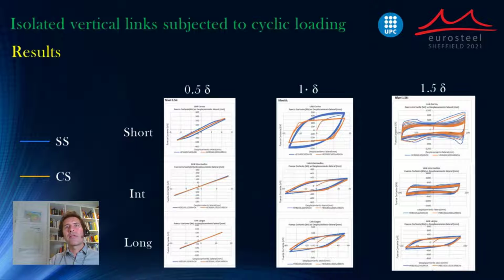And then when we come to the cyclic loading, here we can see in the slide 9 pictures corresponding to short, intermediate, or long links, and corresponding to stainless steel and carbon steel for the sake of comparison, in which we have three levels of loading: 0.5 delta, 1 delta, and 1.5 delta. For the former, we can see that the response is quite linear in all cases, especially in long. There is a certain drift in the linearity for the case of short elements, which were stiffer and in which displacements are more reduced, of course.